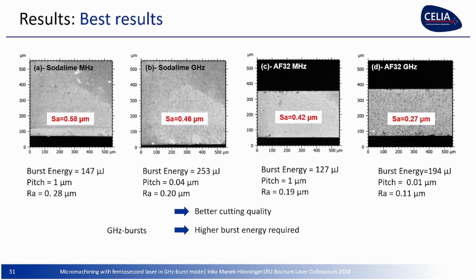You need a higher burst energy for gigahertz. And here you need more than here, and here you need more than here. It's logical because you have less energy in your individual pulse, so it has to be enough to do a pre-cutting zone. And a higher overlap is required, so the pitch is lower in the gigahertz case. That means if you want to go to better quality, you have to do gigahertz. However, it's slower because the pitch is lower.